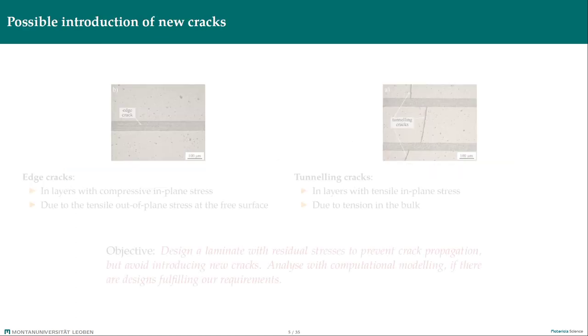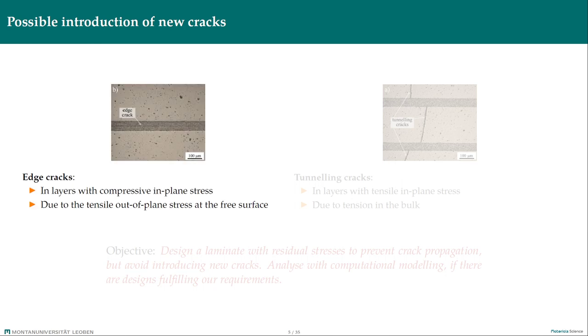As I said, as a consequence of suboptimal design two new cracks might arise. First kind are so-called edge cracks which we find in layers with compressive in-plane residual stresses. Yes, compressive residual stresses are positive things which we desire but unfortunately they transform into tensile out-of-plane residual stresses at the free surface of the specimen's side. When a crack initiates at the surface it channels around the side and extends further into the depth, stopping only after the Griffith's energy criterion is no longer fulfilled or due to the vanishing out-of-plane stresses.